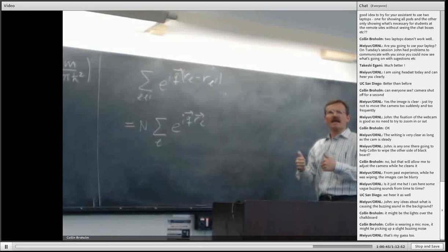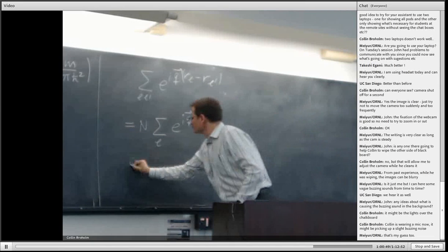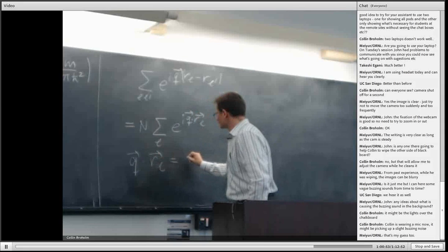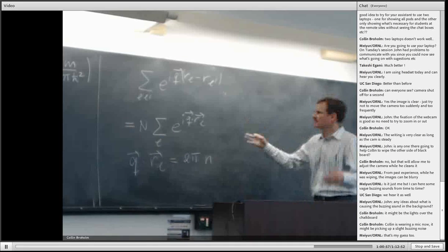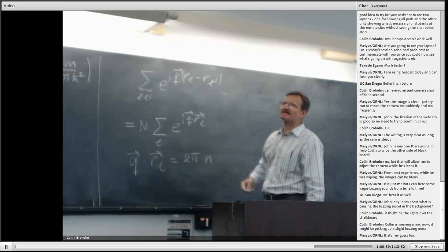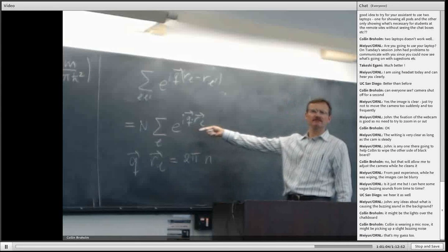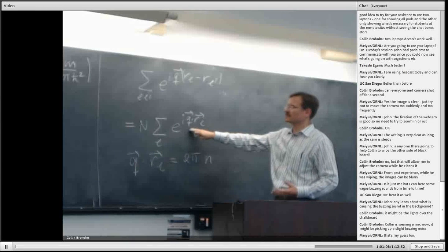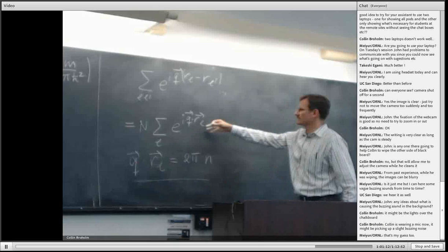However, it does not happen if this dot product of q with R L happens to be equal to 2 pi times an integer. Then all of these just become 1s, and you're constantly getting the same thing, which will eventually add up to something terribly large. So you have a function which is generally 0, but then it has these very special places where it ends up producing something very large.